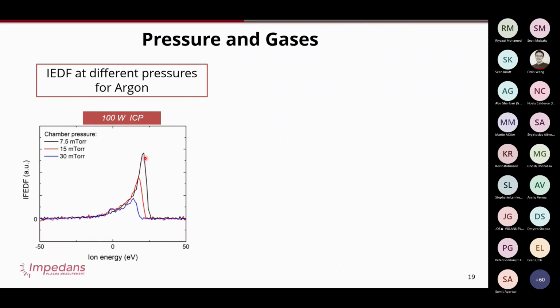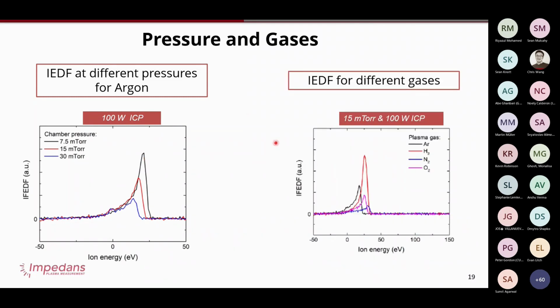Let me show you another example for different gases. Under the exact same conditions, 15 millitorr, 100 watts on the top, for different gases you get different behaviors. In this case, the ion flux was highest for hydrogen. I suppose that kind of makes sense. Hydrogen is the lightest gas there. You're going to have the most particles per second moving, right? It's going to be most reactive to what's going on.